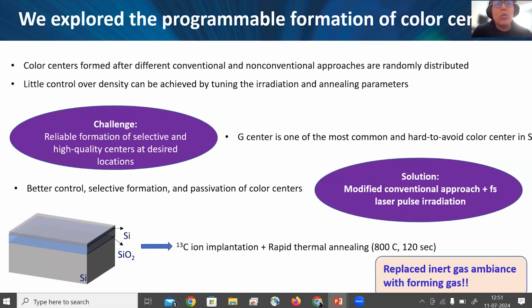Now coming back to the main issue that we have been trying to solve, which is how to make these color centers at desired locations with high quality. If you compare with what people have been doing so far, when they do ion implantation and rapid thermal annealing, you end up having these color centers randomly located in your lattice. So they are not at local sites or wherever you want them.